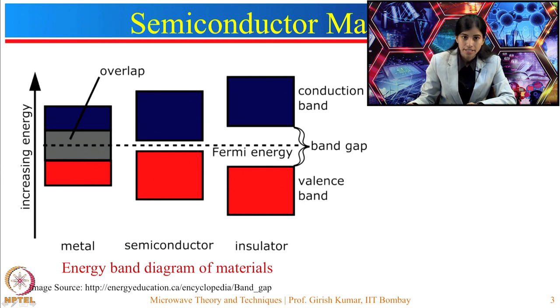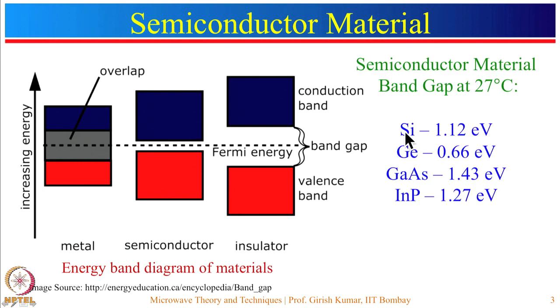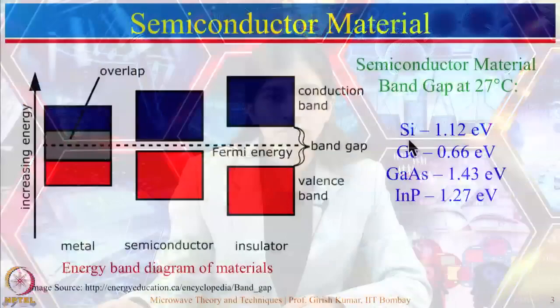The most commonly used semiconductor material is silicon, with a band gap of 1.12 eV. For germanium it is 0.66 eV, for gallium arsenide it is 1.43 eV, and for indium phosphide it is 1.27 eV. Silicon is the most widely used, and most electronic devices are made from it. However, silicon and germanium are not suitable for the microwave frequency range because they suffer from the problem of minority charge carrier storage, which does not provide desirable performance at microwave frequencies.